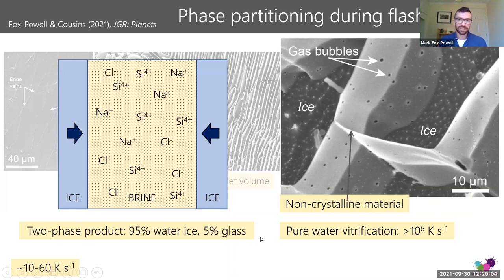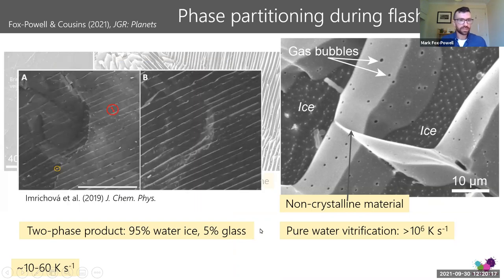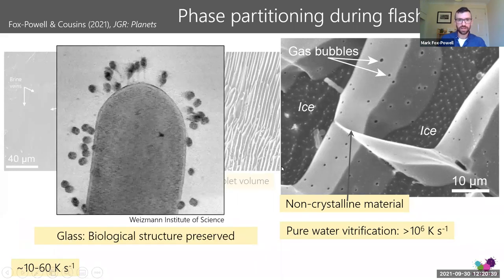So what we are seeing here is a two-phase product, one that contains about 95% crystalline water ice and around 5% by volume this really solute-rich glass. This is consistent with other studies. This is an experimental study a couple of years ago, just looking at a sodium chloride solution, and they see something very similar. You have this freeze-concentrated brine which, because of its very high viscosity, actually inhibits crystallization. So you have a crystalline ice phase and a vitrified glass phase alongside it. And this could be really significant from an astrobiology point of view.